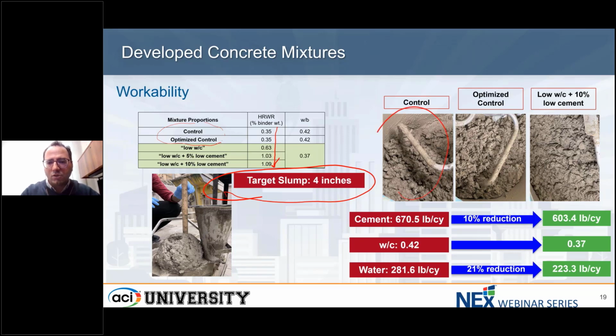So we have control, we have optimized control, and at the right side we have low water cement ratio, 10% low cement mix. So you see in control one, you see a little bit of bleeding in the system, but by optimizing the aggregate, we get a more cohesive mix design. So these are some metrics. I didn't want to bore you with a table. It's more about how we move from the higher content to lower content.